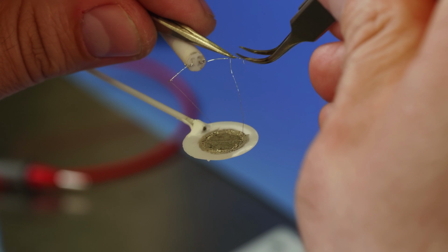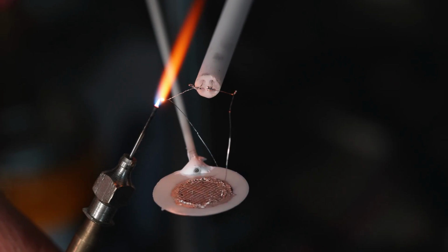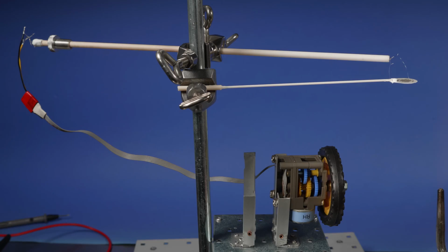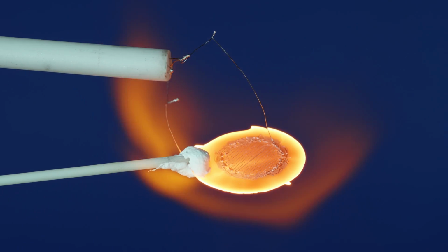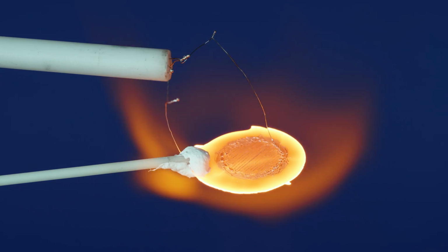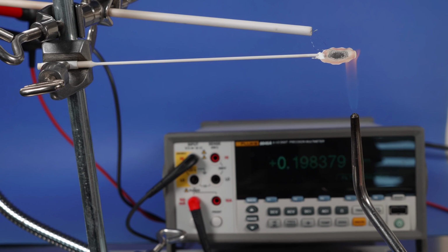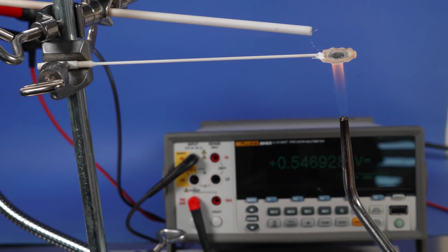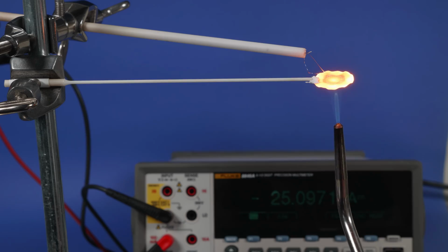Here we have assembled a small demo single cell. A methane flame heats it up and provides a flow of fuel at the anode. Of course, in a real SOFC stack, fuel is consumed more efficiently. Solid oxide fuel cells operate at temperatures from 600 to 950 degrees Celsius. Maximum voltage obtained was 0.94 volts, which is close to the theoretical value in a dual chamber cell. Current was up to 25 milliamperes.